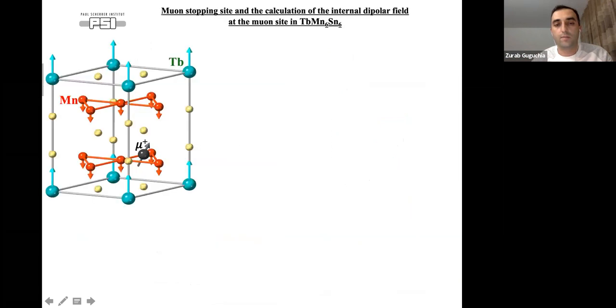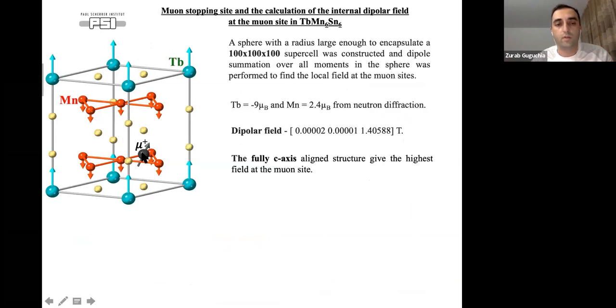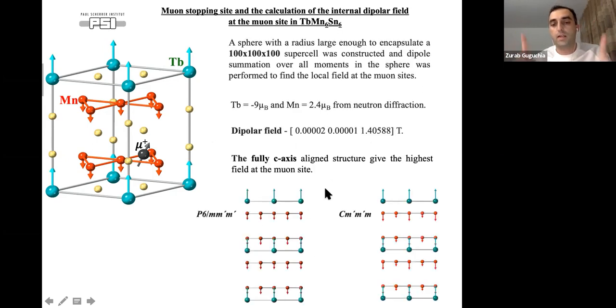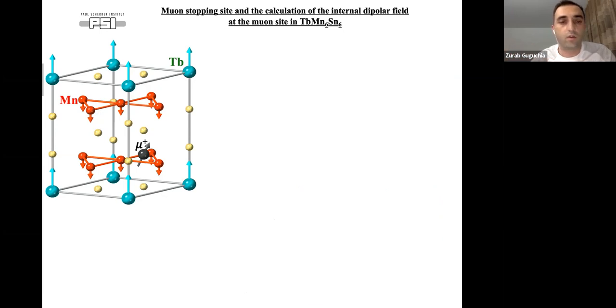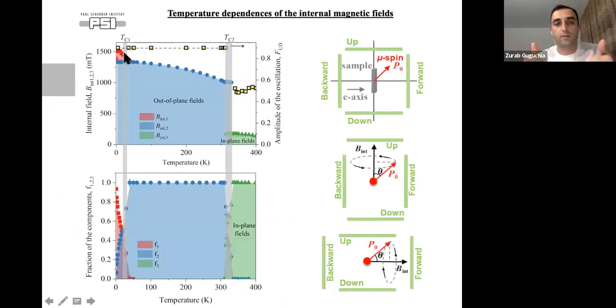To see more precisely what kind of structures we have, we again did a muon stopping site calculation, and we estimated the dipolar field at the muon site by summing up all the dipolar moments in a large supercell. The moment sizes we know from neutron diffraction, which we measured on exactly the same crystals. We find that the dipolar field, if you assume the fully C-axis aligned structure, is about 1.4 Tesla. So it shows a C-axis aligned field at the muon site, and the value agrees very well with experiment. I mean, it's pretty close. But any other kind of structure that we calculated, and any type of arrangement of the terbium and manganese, would result in a lower local field at the muon site. So from this we concluded that this highest frequency structure which we got at low temperatures is a C-axis aligned static structure.